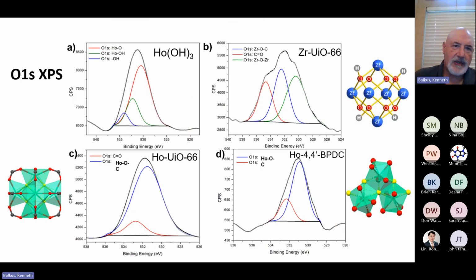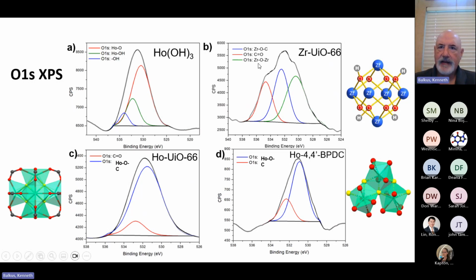Also, you could go the other way and say, well, if it's not fluorine, it would have to be an oxygen bridge. And in fact, if you use zirconium, what you get is clearly an oxygen bridge. And so that zirconium, oxygen, zirconium, in the top right here, the green peak, that binding energy is for the oxygen bridges in the cluster.